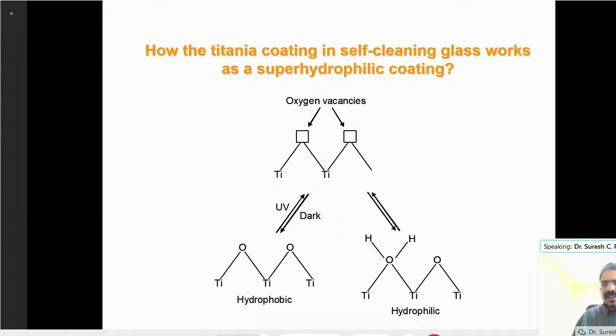So once you have oxygen vacancies, the water has a lone pair of electrons. The water can easily fit on these oxygen vacancies. So we are moving from hydrophobic to hydrophilic. Because of the oxygen vacancies, the water molecules can easily fit on those surfaces. So that is how we can convert a hydrophobic surface to a hydrophilic surface. The beautiful chemistry there.